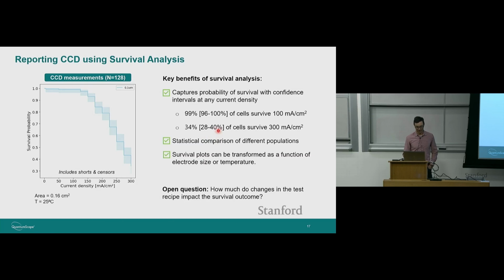So what you're seeing here is 99% of the probed material surviving at 100 milliamps per square centimeter. Let me put that number in context for you. A battery doing fast charge that I showed earlier would be passing 20 or 25 milliamps per square centimeter. So about a quarter of that level.